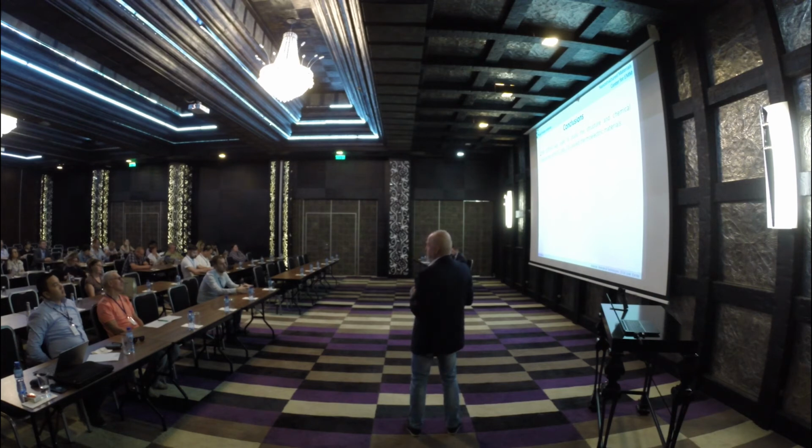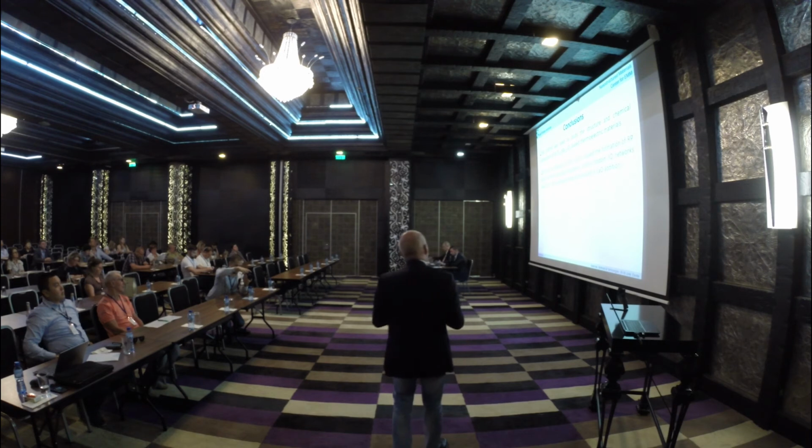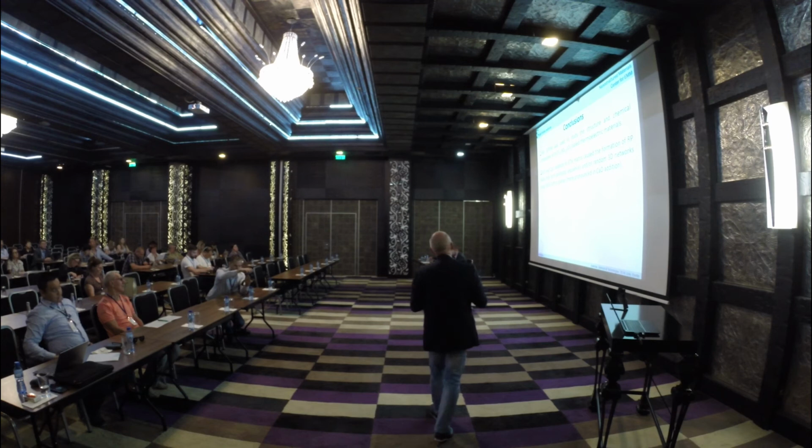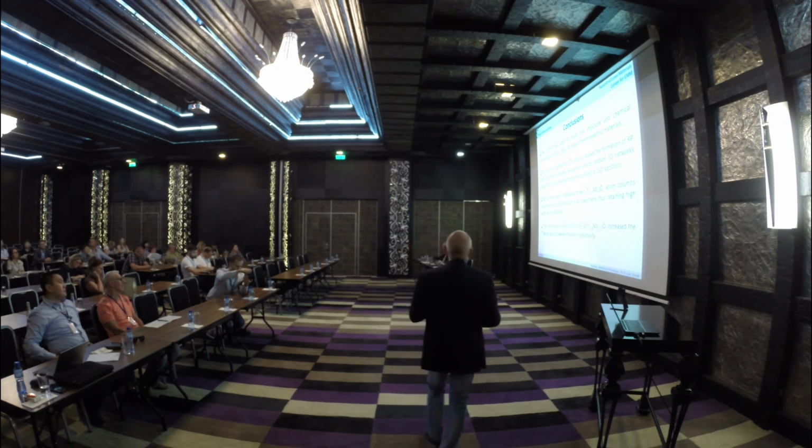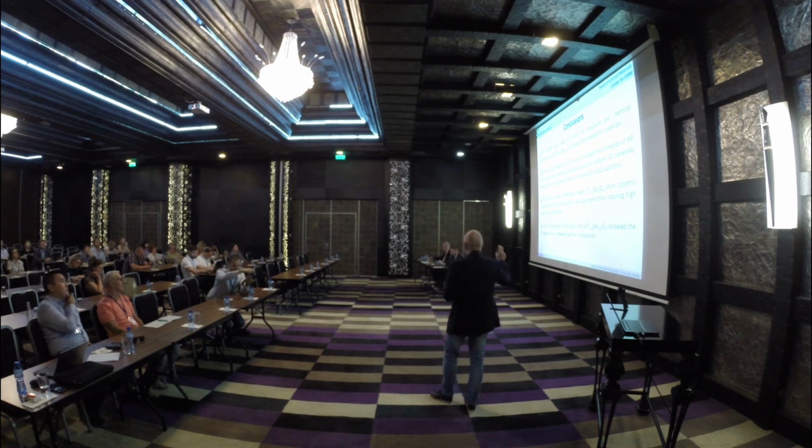So this is, in very short, a little bit of conclusion. Of course, microscopy is extremely important in any atom-resolved characterization, either structural or chemical, of any materials. When we add strontium oxide and calcium oxide, we form polytypic sequences or isolated faults. Also, the concentration of titanium and niobium was different on the B sites, and this approach to incorporate this type of faults into the matrix turned out to be beneficial, so that we were able to increase the figure of merit, or ZT, of the materials.